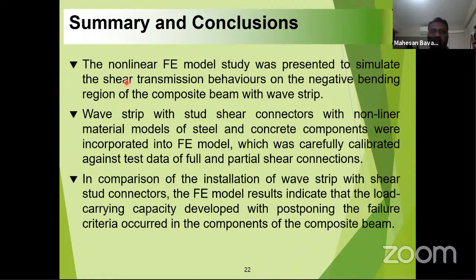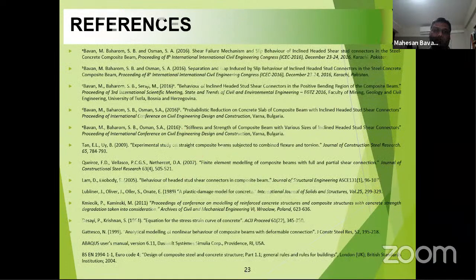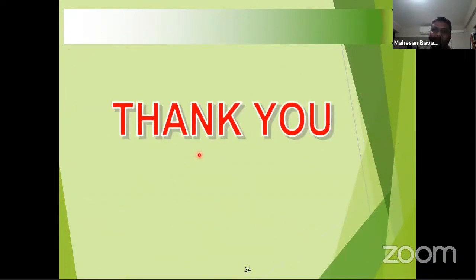Based on this, we draw the summary and conclusion. A nonlinear finite element model study was presented to simulate the shear transmission behavior in the negative bending region of the composite beam with wave strip. Wave strip with stud shear connectors and nonlinear material models of steel and concrete composite components were incorporated into the finite element model, which was carefully calibrated against test data of full and partial shear connection. In comparison with the installation of wave strip with shear connectors, the FE model results indicate that the load carrying capacity developed, with postponement of the failure criteria occurring in the components of the composite beam. So this is our summary and conclusion today, and some of the references I used. Thanks everyone for watching my presentation.